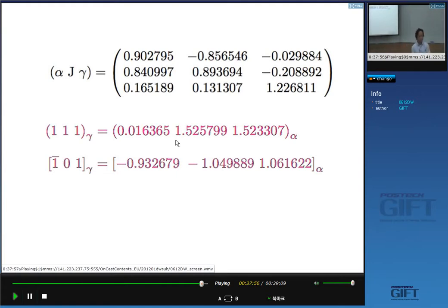So this indicates that when you consider the orientation relationship between austenite and martensite, the orientation relationship is close to Kurdjumov-Sachs, but does not exactly match, which I told you is one of the problems we have to solve to understand the martensite transformation. The orientation relationship between austenite and martensite is irrational. It's close to certain orientation relationships like Kurdjumov-Sachs or Nishiyama-Wassermann, but not an exact match. The phenomenological theory perfectly explained why it happened.